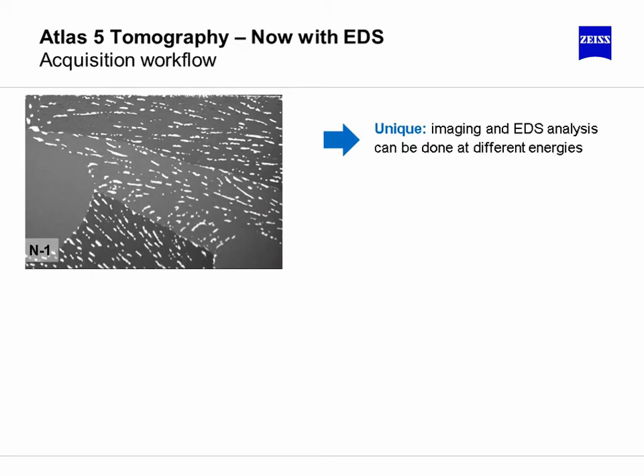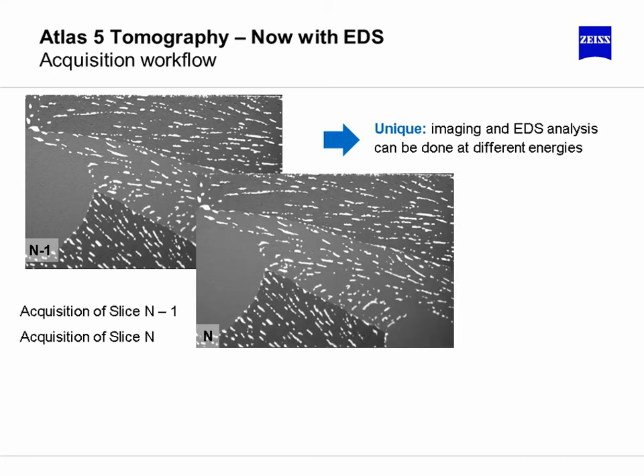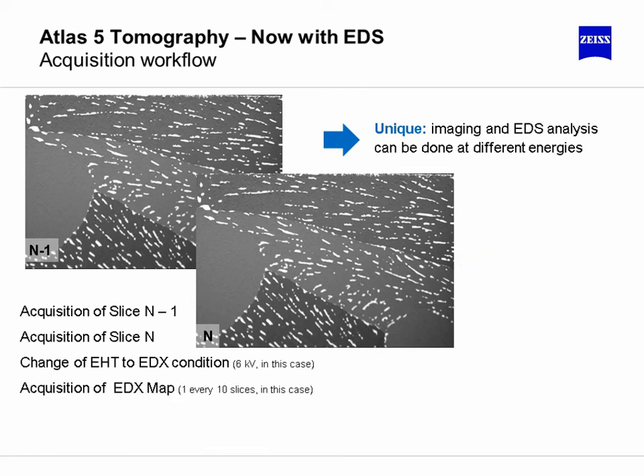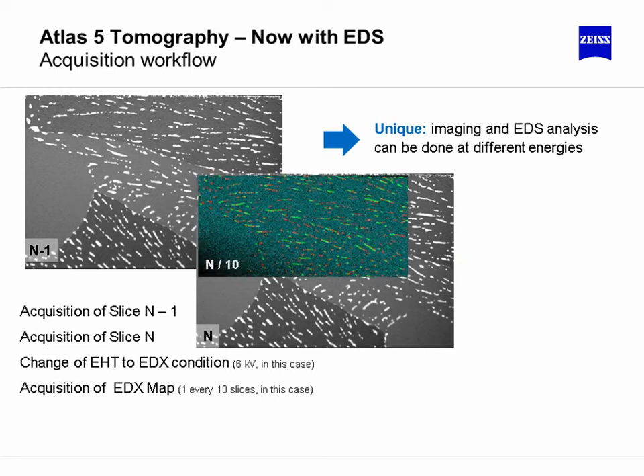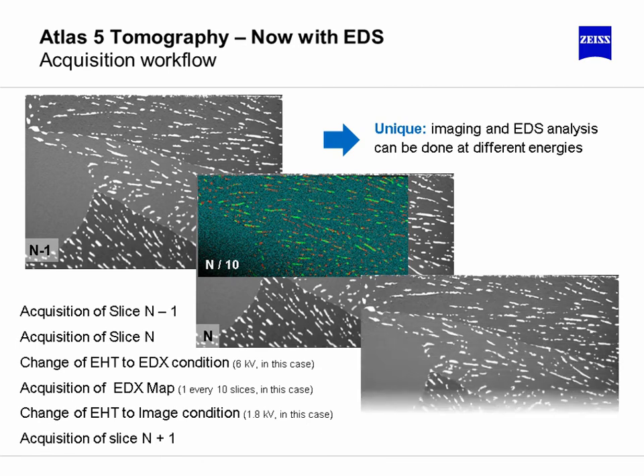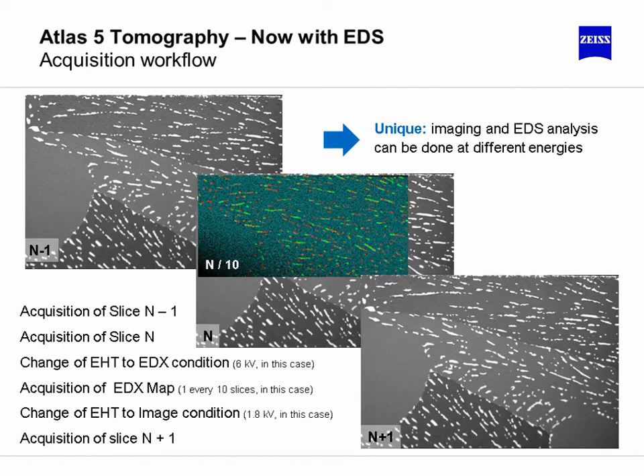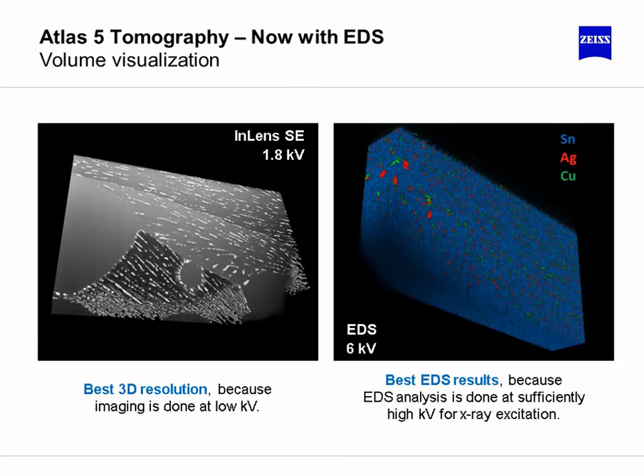The workflow is described in more detail on this slide. So here you see the acquisition of the image N-1. The next slice would be slice number N. Now the landing energy is changed from imaging conditions to EDS conditions. In this case, we switch from 1.8 kilovolts to 6 kilovolts, and an EDS map is acquired. After acquisition of the EDS data, we change back to the imaging conditions, 1.8 kilovolts in this case, and acquire the next slice image. This process is iterated a number of times, and you end up having a 3D data stack, which can then be reconstructed.